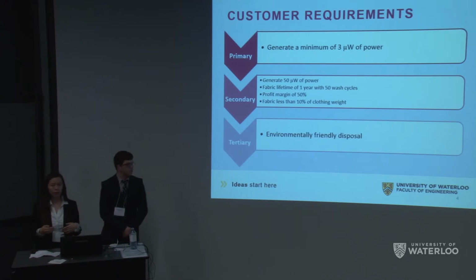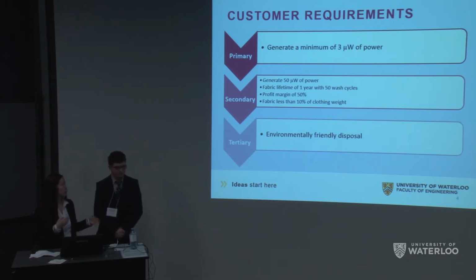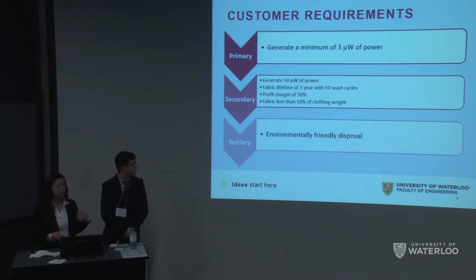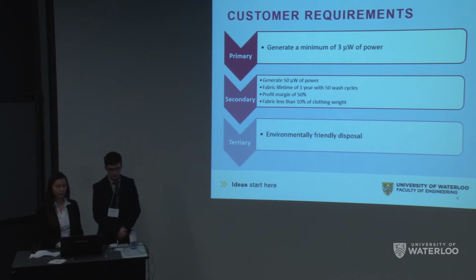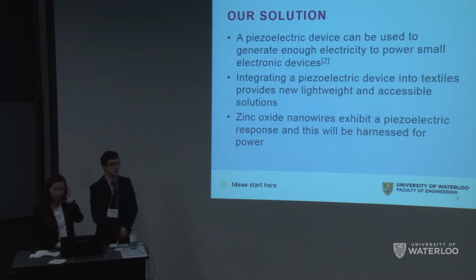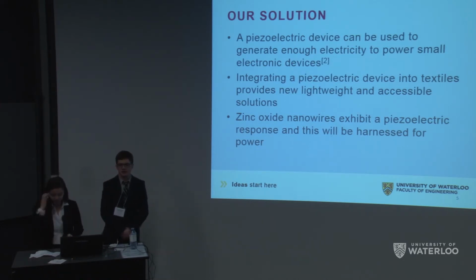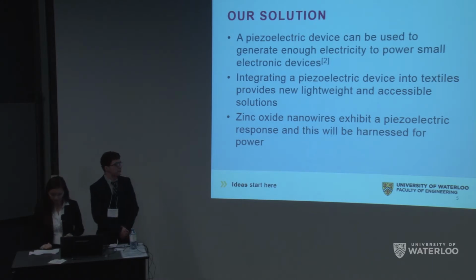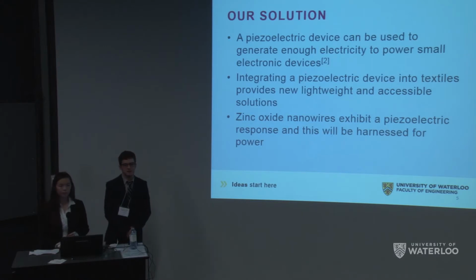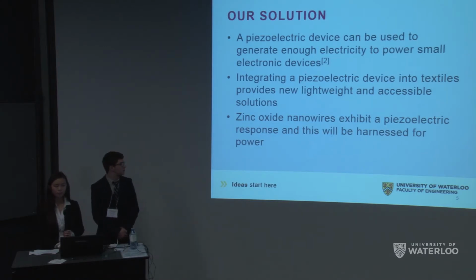We also wanted our prototype to be durable, which is where the fabric lifetime of 1 year with 50 wash cycles comes from. And the other ones are just we want it to be lightweight, we want it to be cheap, and then the tertiary goal is to have environmentally friendly disposal. So in order to meet these goals, we decided to utilize the piezoelectric effect for our solution. The piezoelectric effect allows you to generate electrical power without the need of a bulky battery pack or a replacement. We chose to use zinc oxide because it exhibits the piezoelectric effect, and we chose to use cotton as our fabric due to its morphology.